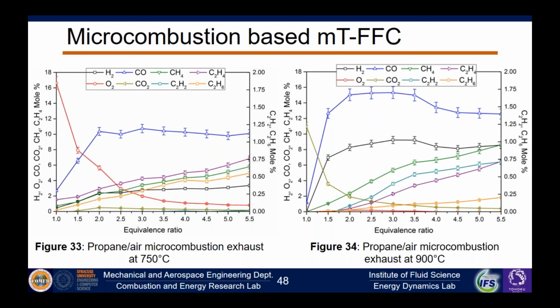But at 900 degrees, we see a real change. These reactions that we're talking about are highly temperature dependent. And so as we start to increase the temperature, we start to see carbon dioxide is really significant concentration, at least at stoichiometry. We see much higher carbon monoxide concentration, hydrogen concentration, and ultimately kind of a change here.